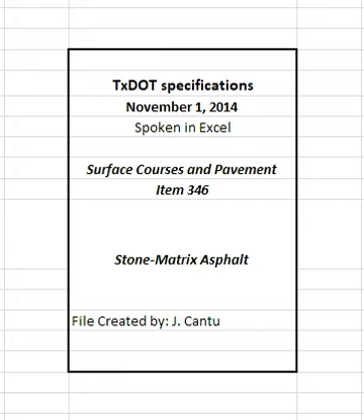4.9.2.2.3 Asphalt binder sampling. Obtain a 1 quart (1 gallon for AR binder) sample of the asphalt binder for each lot of mixture produced. Obtain the sample at approximately the same time the mixture random sample is obtained. Sample from a port located immediately upstream from the mixing drum or pug mill in accordance with Tex-500-C, Part 2. Label the can with the corresponding lot and sublot numbers and deliver the sample to the engineer.